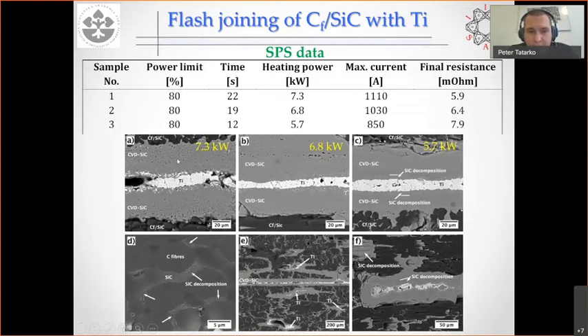You can see very clearly that the power was so high that we actually decomposed the CVD silicon carbide matrix and the coating. You see here all these holes. Also in this case, it was a decomposition of the silicon carbide. So in other words, the power was really too high, the temperature inside was extremely high. But we also saw that with decreasing power, here is the lowest power, the decomposition is less significant than in this case. So we could see some clear effect of the heating power.